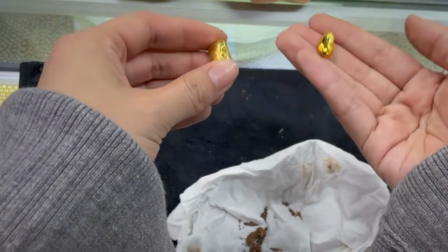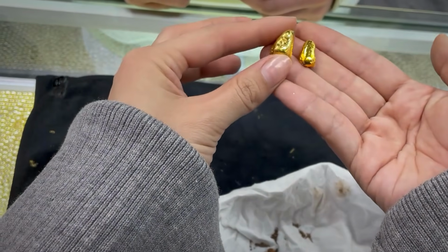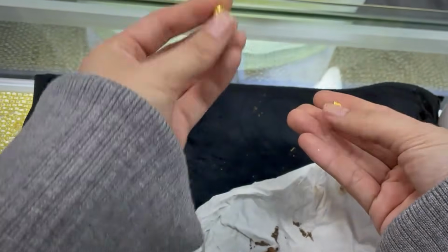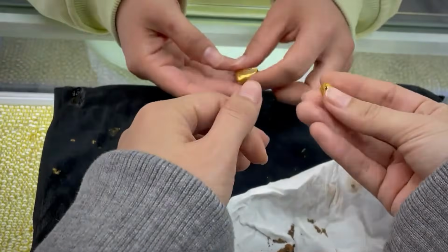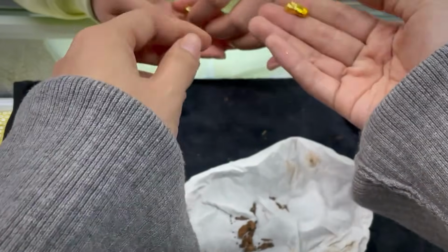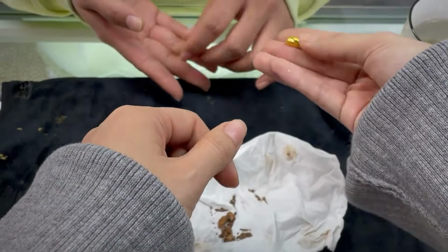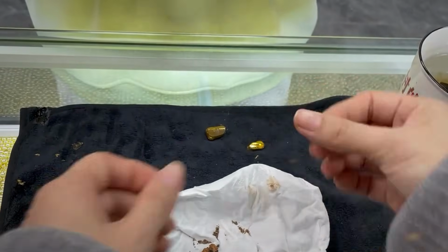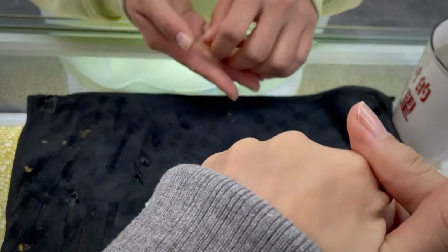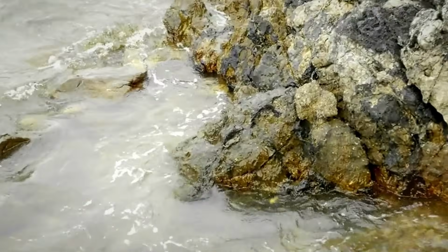Once cooled, the slag is cracked off, and the remaining lead button is placed in a small cup made of bone ash, a cupel. In a second, hotter fire, the lead oxidizes and is absorbed by the cupel, leaving behind a bead of gold and possibly silver. That bead is your proof. It may be smaller than a lentil, but it carries absolute weight.